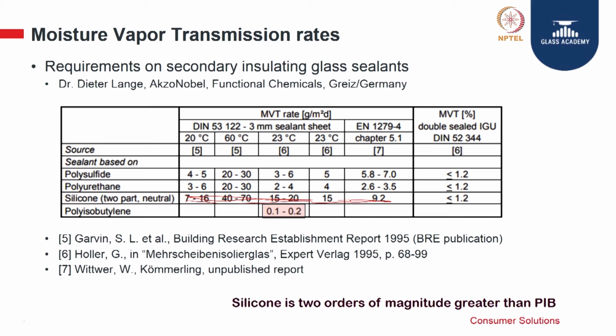So, these are all permeable to moisture to a certain extent, but if you see at room temperature of 20 degrees, and also at high temperatures, the difference between the organic and the silicone ratios gets reduced, because organic sealants tend to behave differently with different temperatures to a much larger extent compared to silicone. But the best seal, which has the lowest moisture vapor permeability, is polyisobutylene. A system made with the best possible secondary seal, which is silicone, and the primary seal PIB gives you a long term durable DGU.